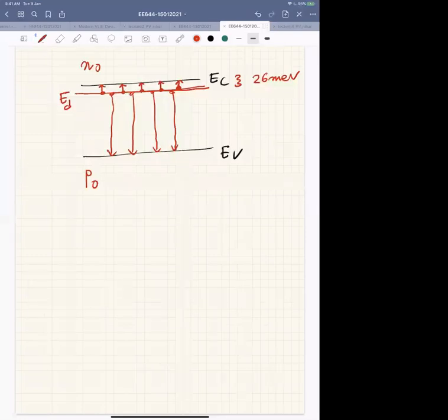You will make an extrinsic semiconductor. See, in the implantation process, your crystal structure is damaged. Then you do the annealing, and when you do annealing, the bond formation happens. That means the atoms are periodically arranged again, but during this periodic arrangement, some of the silicon atoms are replaced by arsenic. Arsenic has 5 valence electrons and silicon has 4, so they form covalent bonds and 1 electron is free. That means every defect state has 1 free electron.